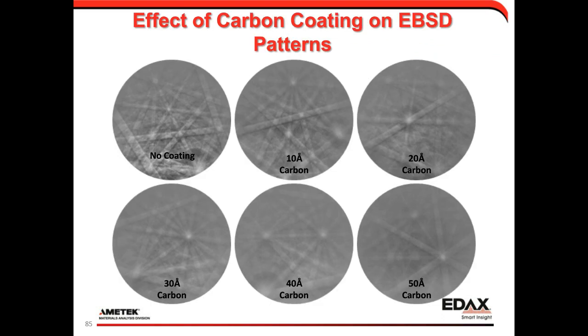So what can we do to minimize this charging effect on non-conductive samples? One of the easiest and traditional things to do is to put down a conductive coating. Generally I recommend a carbon coat over something like aluminum or gold palladium. The reason is that carbon has a lower atomic number, so it's not going to scatter the electrons coming out of the diffraction as much as a gold coating would.